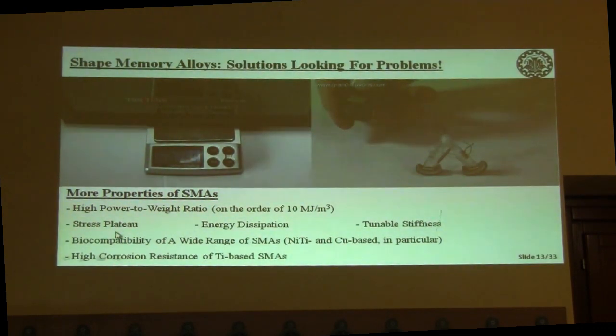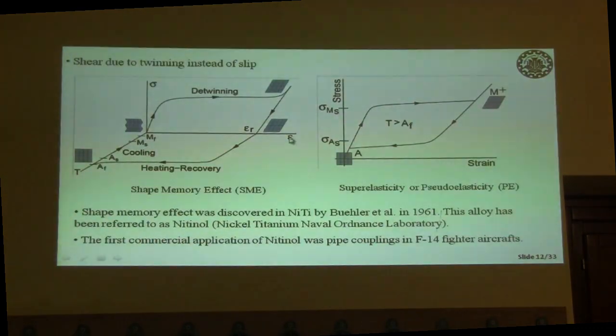We have some stress plateau. If you look at the typical stress strain, no considerable strain hardening occurs in the response of the material. This stress plateau is more sensitive to temperature than the extent of strain. This means that in a variety of different applied strains, I can have almost constant stress. And I will explain the benefits in biomedicine and biomedical applications.